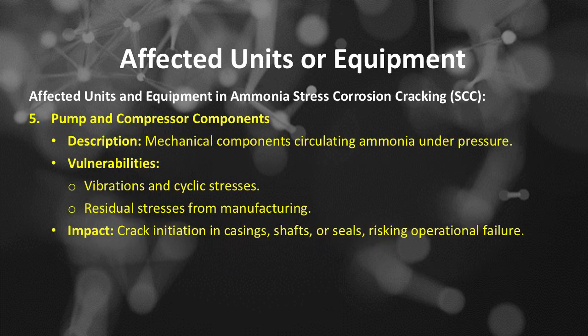Number 5 of affected units and equipment in ammonia stress corrosion cracking is pump and compressor components. These mechanical components circulate ammonia under pressure. The vulnerabilities of these pump and compressor components include vibrations and cyclic stresses, and residual stresses from manufacturing. The impact would be crack initiation in casings, shafts, or seals, risking operational failure.